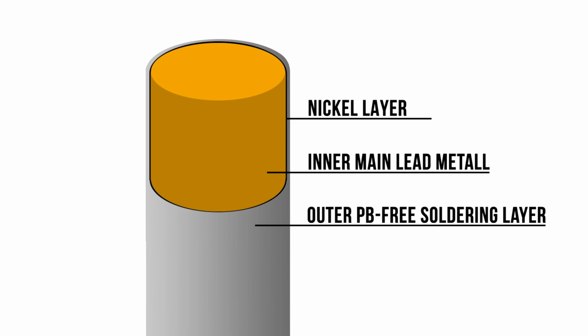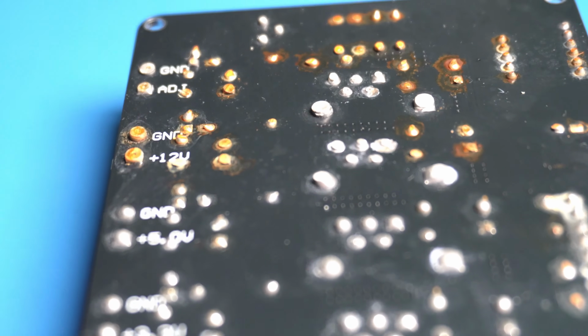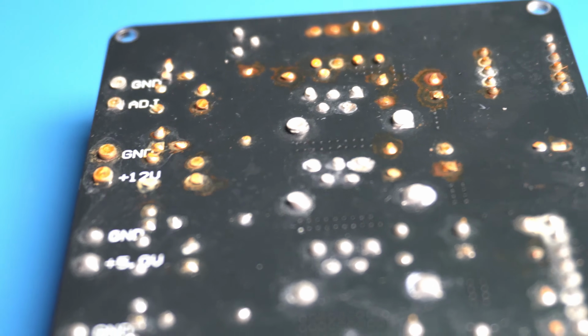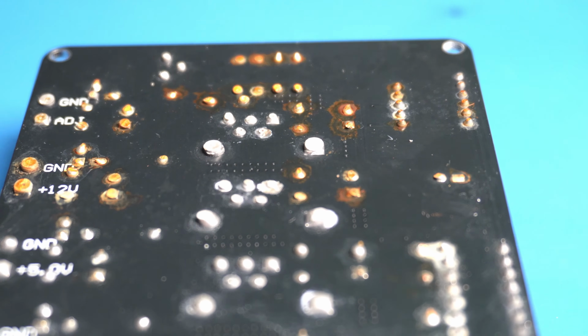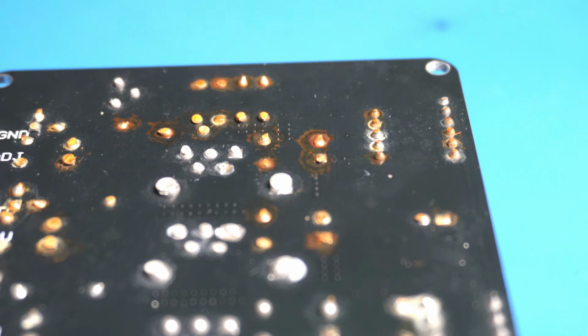Internally, these leads may have a nickel layer to bond the base metals to the finish coating. On the outside there is a finish coating, usually a lead-free alloy, which makes soldering DIP components easy for us. It's almost impossible and pointless to determine the base metal from datasheets. They usually specify only the finish coating layer, so if you don't want the leads to rust, after cutting them, always resolder cut-off leads to seal the base metal from corrosion.